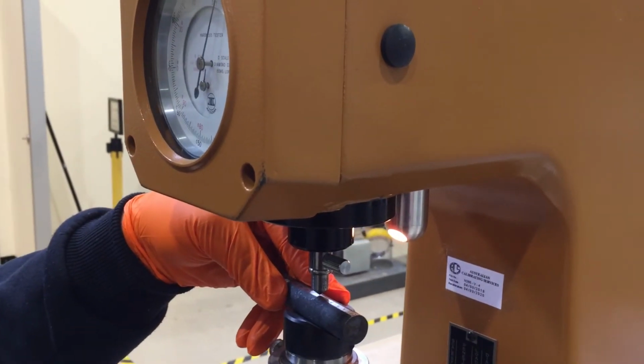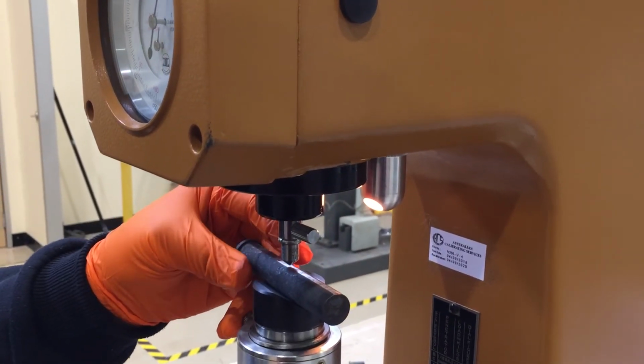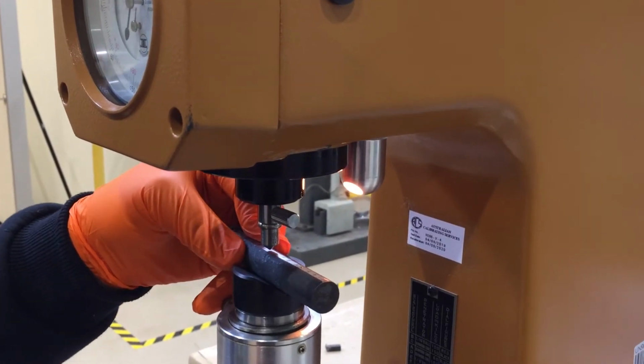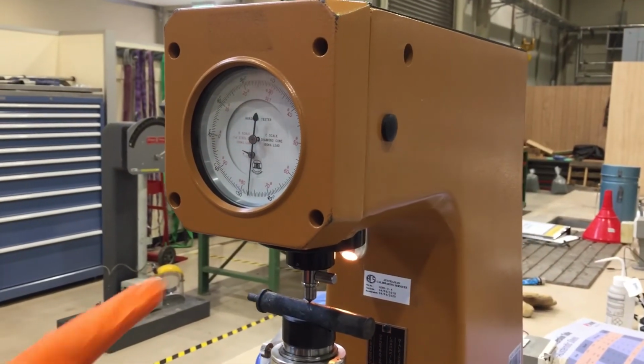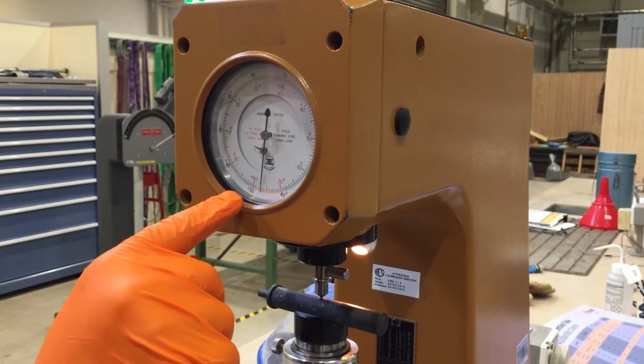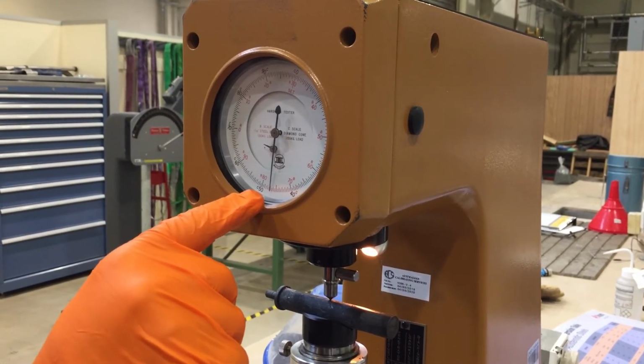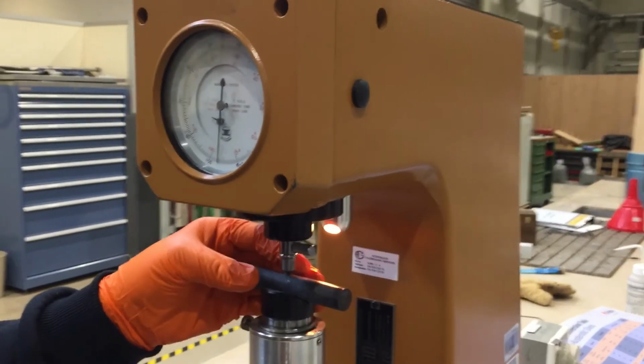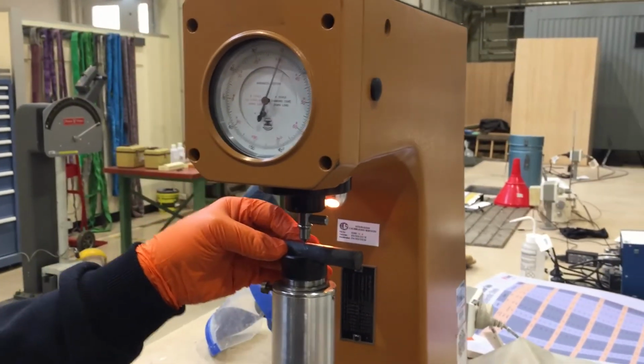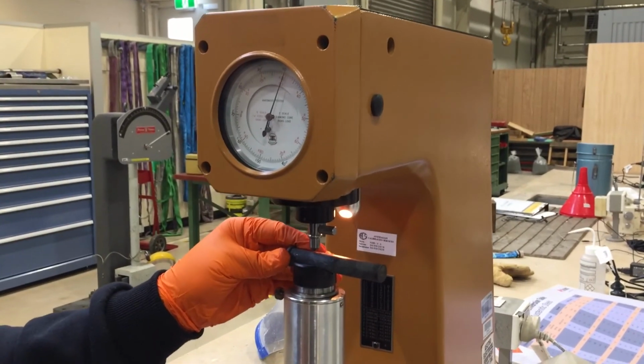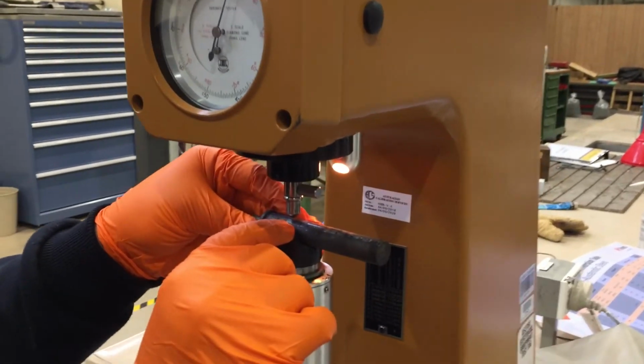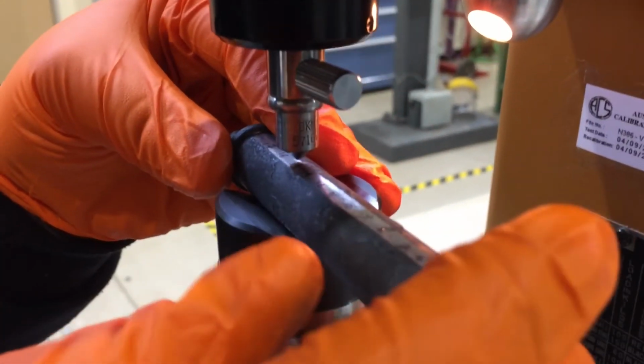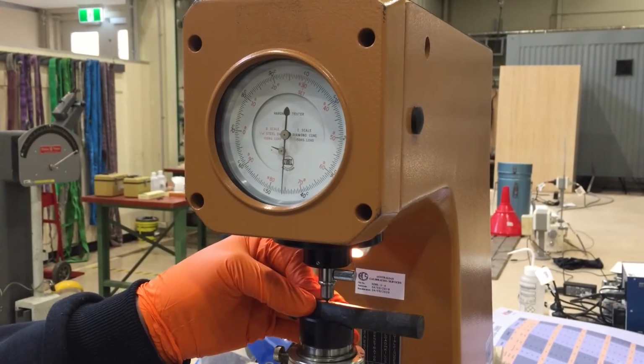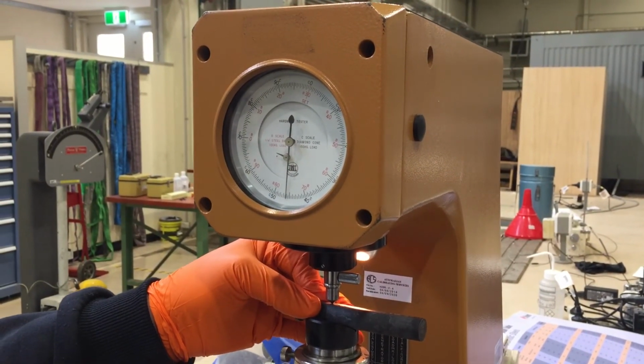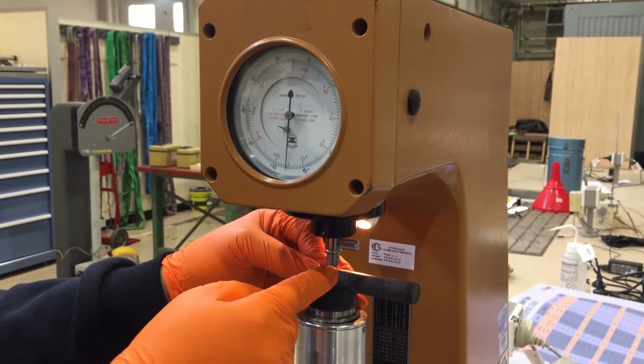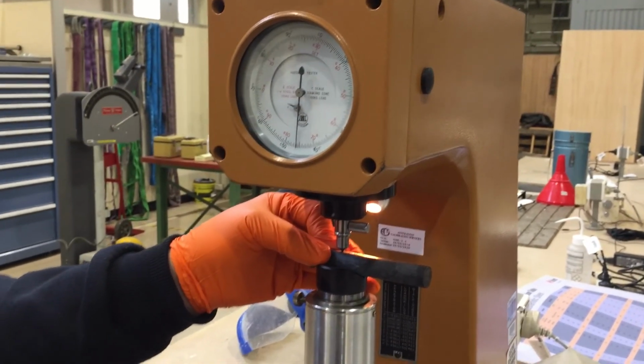And now we're gonna go to location, let's say 11, which is a bit far. So now the hardness is much lower, so it is about 47 Rockwell C. Okay, and now if we're gonna move to the beginning of the sample, so now it is location 15, as you can see here. So we're gonna do the indentation here. So this is about 46, which means the rest of the sample has almost the same hardness.